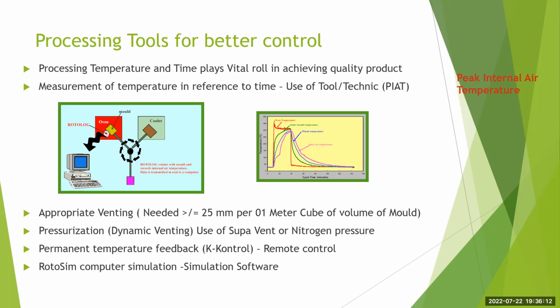In that case, there is a technology called Supa Vent, a silicone venting system which is unidirectional. The vents are designed for a certain pressure, so it creates pressure, but not to the extent that the molds get bulged. It will release the pressure as soon as it goes beyond the required pressure. And sometimes, to avoid oxidation of the material, nitrogen pressure is used in the mold.